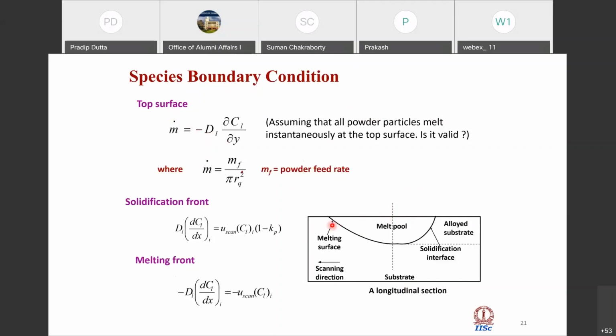And there is a melting surface as the weld pool is moving in this direction, let's say from right to left. This surface is melting, and this is the solidification surface. Okay. Then what happens is here at the melt surface, we have fresh substrate material flux that comes in. And at the solidification surface, which is the alloying interface, due to microsegregation, we have a flux of the species, the added species, which comes in due to microsegregation, because the solubility of the species is different in liquid than in the solid.